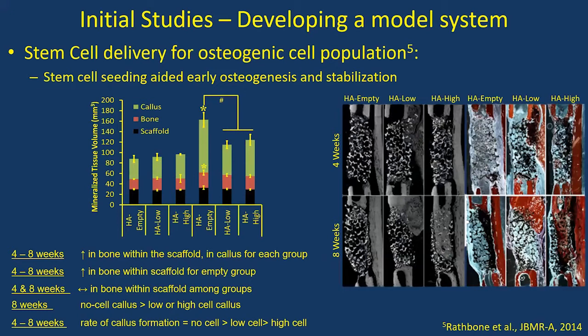The next question was the cell source — stem cells are considered magical in everything. We tested seeding cells at 20% versus 100% scaffold coverage. Like all good science, it turns out we were completely wrong. Having cells on the scaffold actually prevented recruitment of native cells within the body, and because blood vessels didn't grow in fast enough, the seeded cells died. The group without cells actually did much better at eight weeks than groups with cells — which was both interesting and humbling.